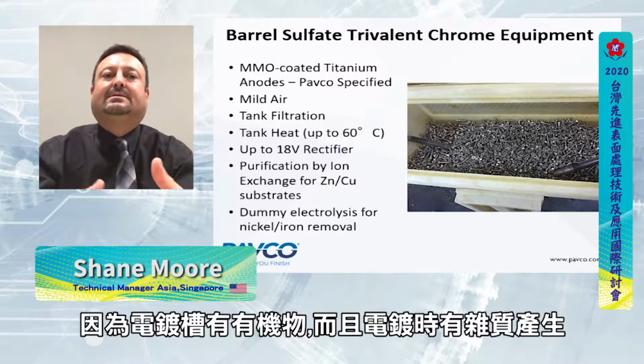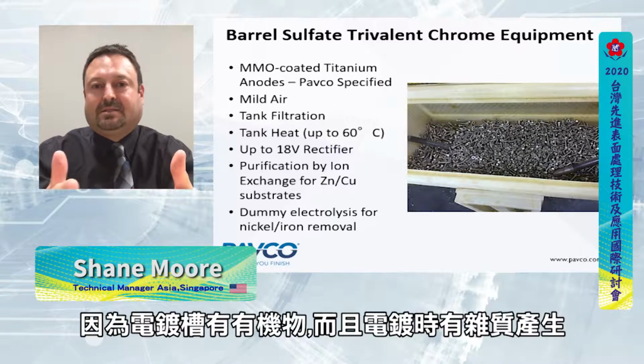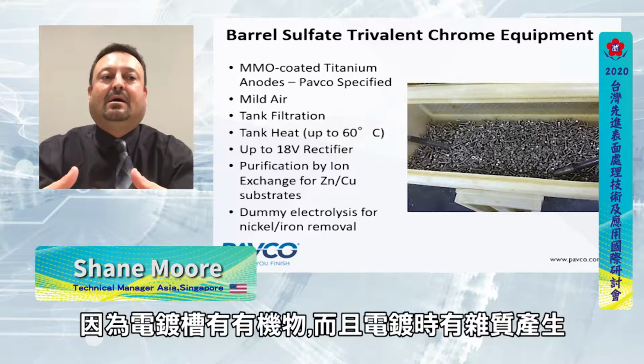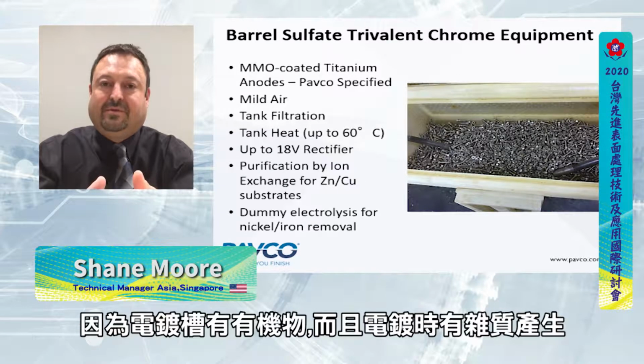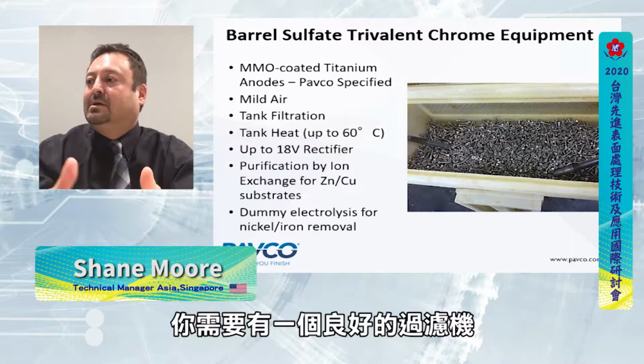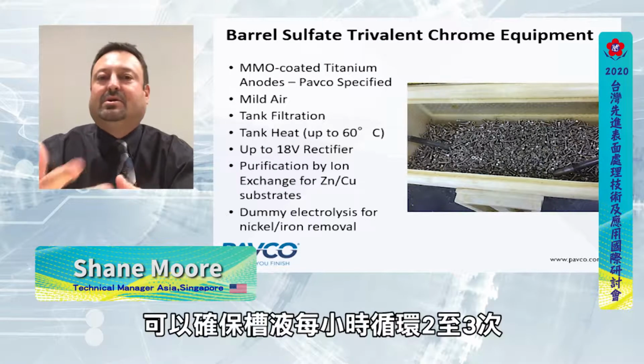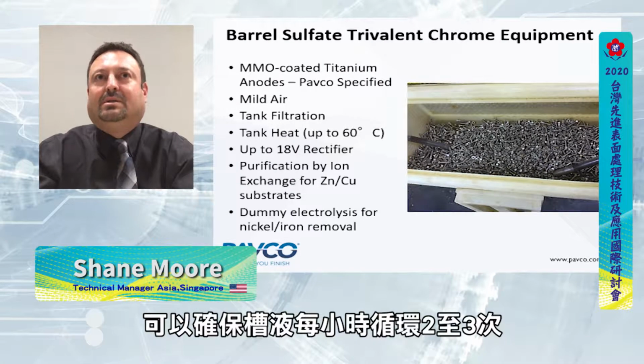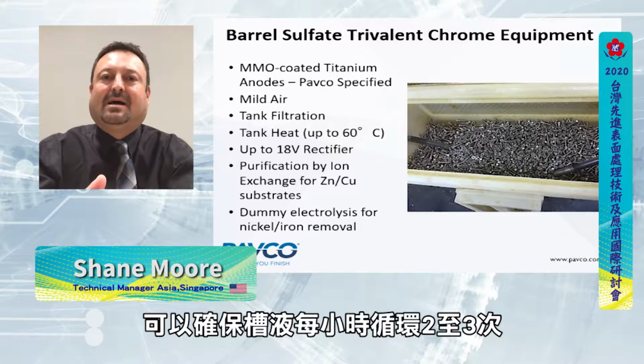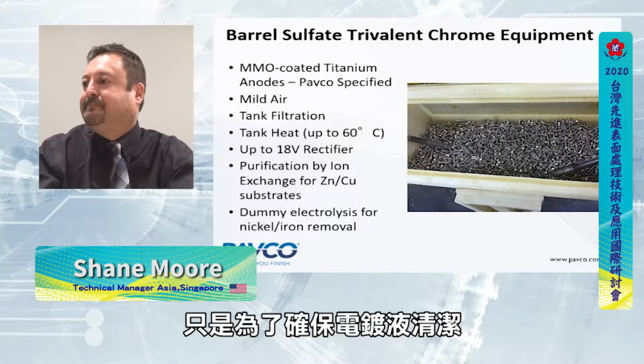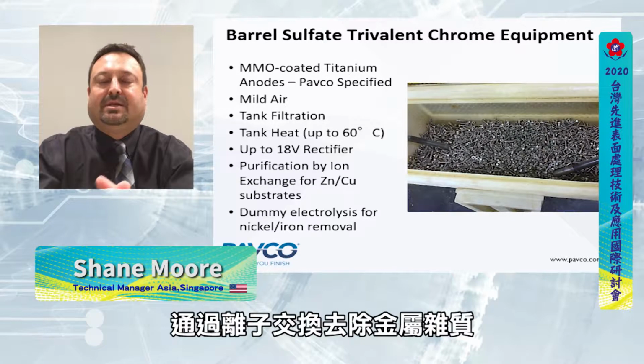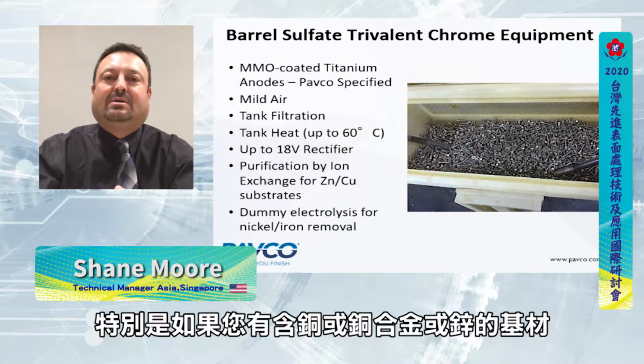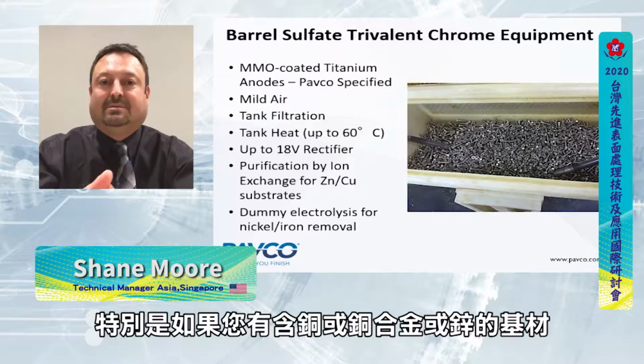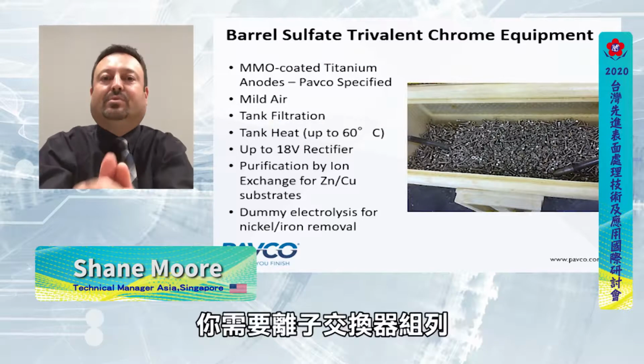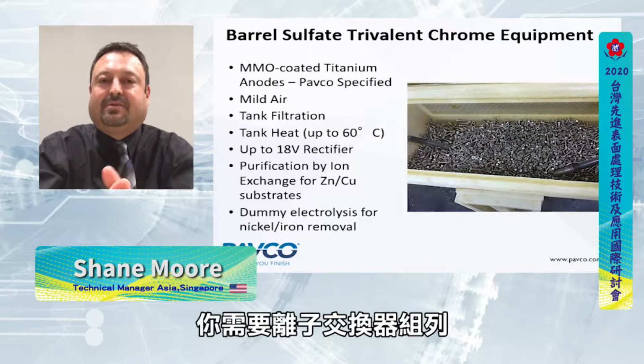As those organics break down from electrolysis, you want to be able to remove that organic contamination. You want a good filter that can turn over the tank about 2 to 3 times per hour. That will keep the bath clean. Purification by ion exchange is needed, especially if you're running parts that are copper or copper alloys or zinc-type substrates like zinc die-cast. You really need to have an ion exchange column for that.